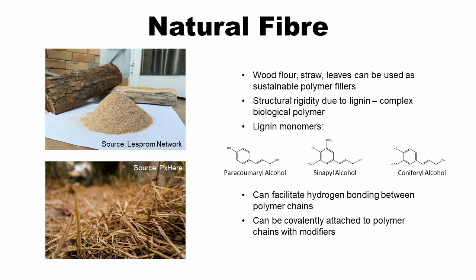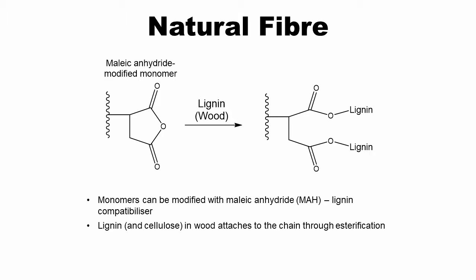Even the things that we often see around us, such as wood, straw, and leaves, can be used as polymer fillers. This is partly due to lignin, a biological polymer, which greatly contributes to the rigidity of plant tissue. The presence of hydroxyl groups in the lignin monomers allows for hydrogen bonding between polymer chains. If a modifier is added, lignin is also capable of covalent bonding. One such modifier that enables strong polymer-wood attachment is maleic anhydride.